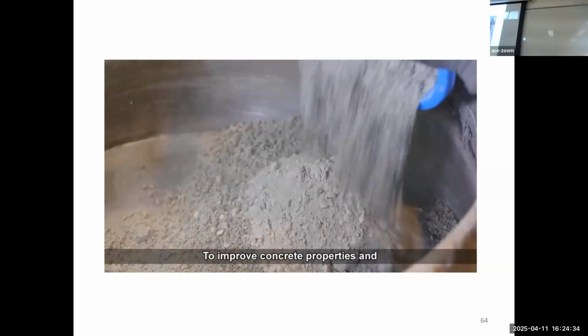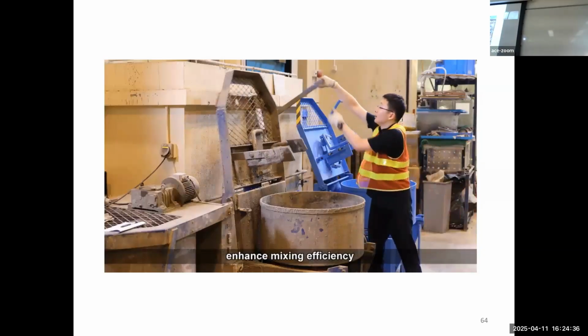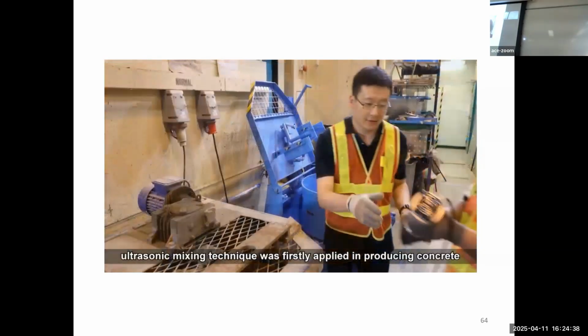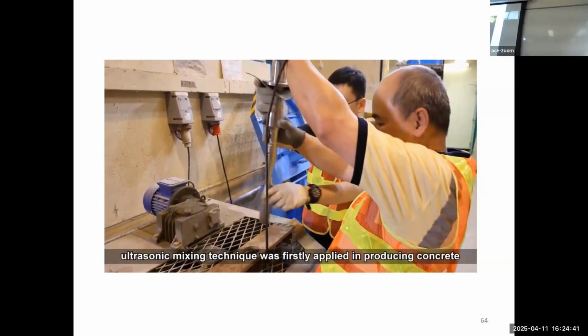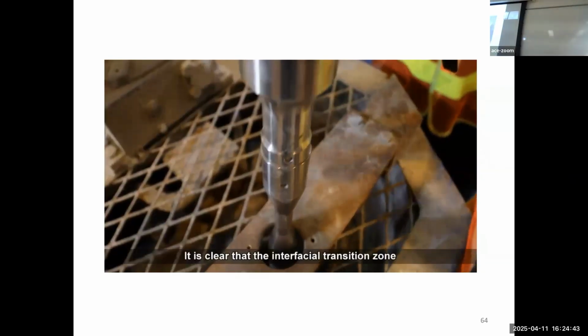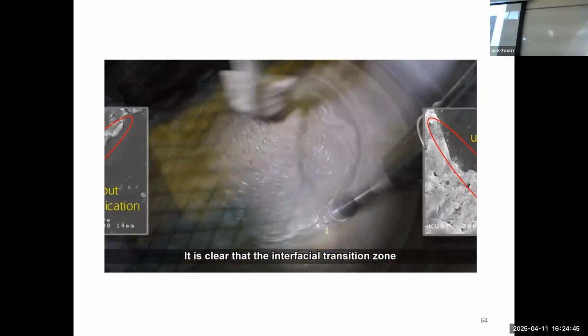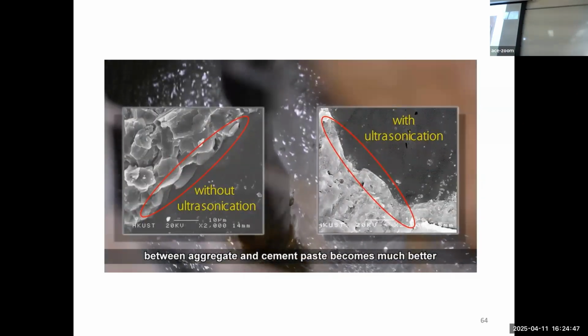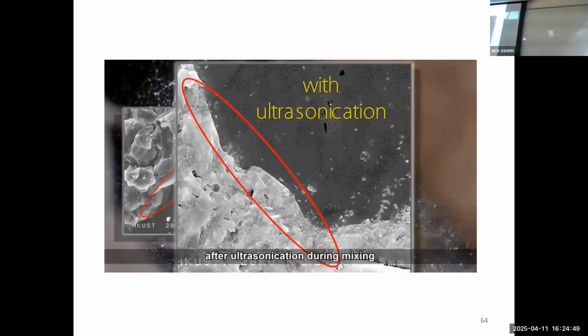To improve concrete properties and enhance mixing efficiency, ultrasonic mixing technique was firstly applied in producing concrete. It is clear that the interfacial transition zone between aggregate and cement paste becomes much better after ultrasonication during mixing.